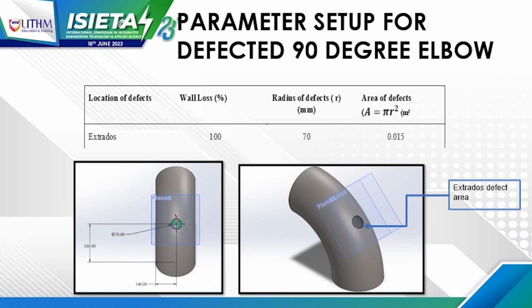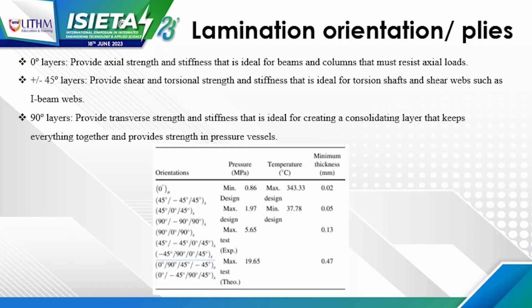This is the defect area with 70 mm of extrados at the extrados location, a defect area with 100% wall loss. It's considered like a pinhole on top of the elbow. For the lamination orientation, we have 3 different degrees to be wrapped around the defected area: 0 degree, 45 degree, and 90 degree. 0 degree can provide axial strength and stiffness. 45 provides shear and torsional strength, and 90 degree provides transverse strength and stiffness, which is ideal for a pressure vessel. So the load that we're going to simulate will range from 0.86 to 19.65 megapascal